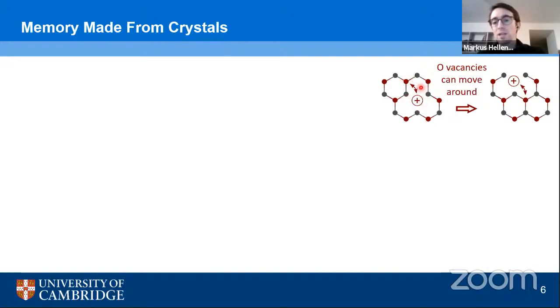So if we can break the bonds of an oxygen atom, for example, to its neighbors, it can switch place with the oxygen vacancy. Then we're in this situation, and effectively the oxygen vacancy moved up through the material. Now, because of the distribution of atoms and electrons in the material, the oxygen vacancies carry a positive charge compared with their surrounding, and we want to make use of this as well.